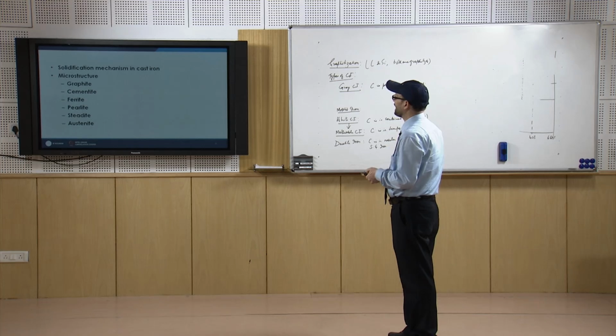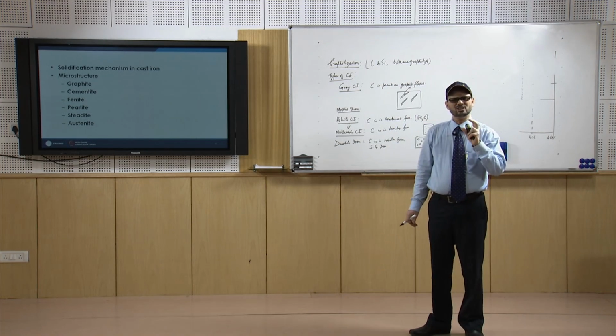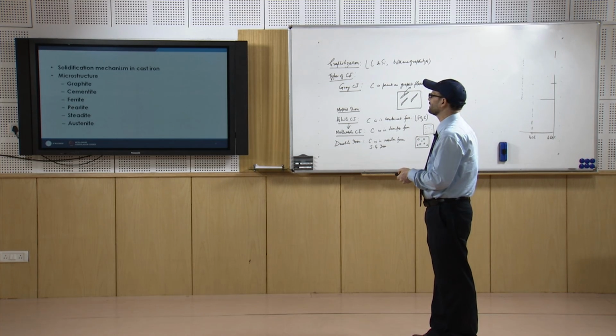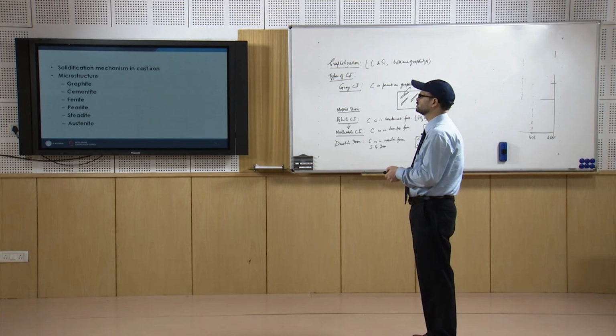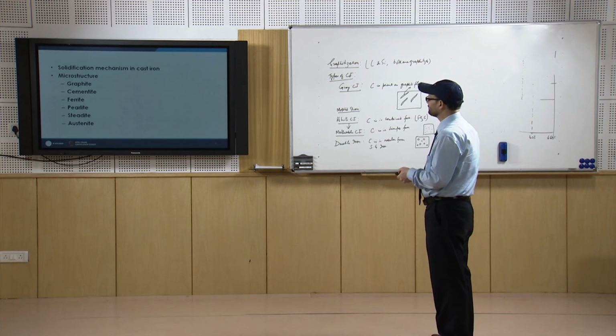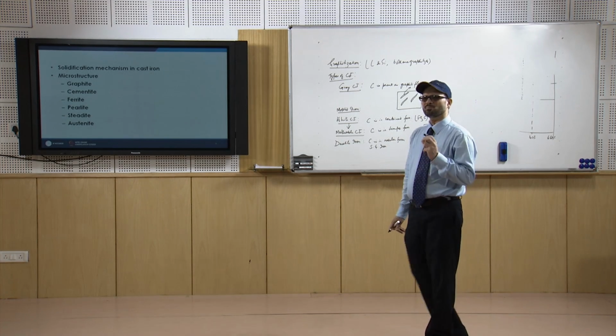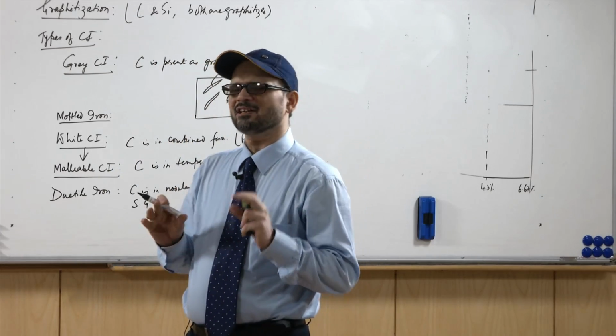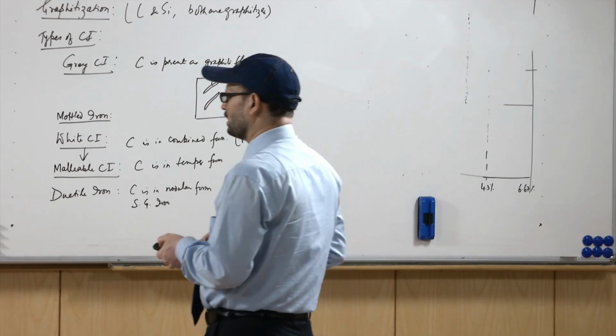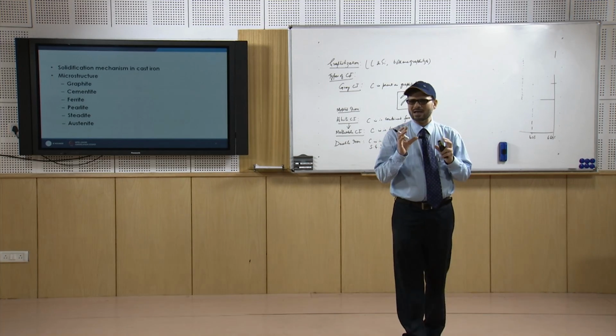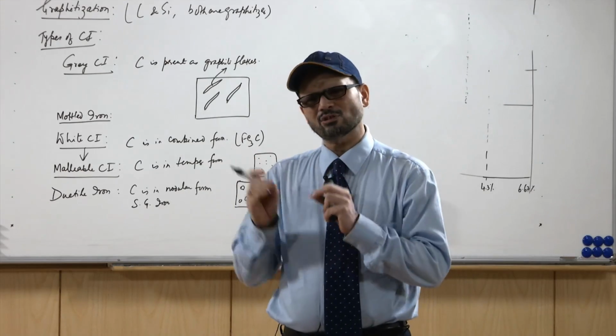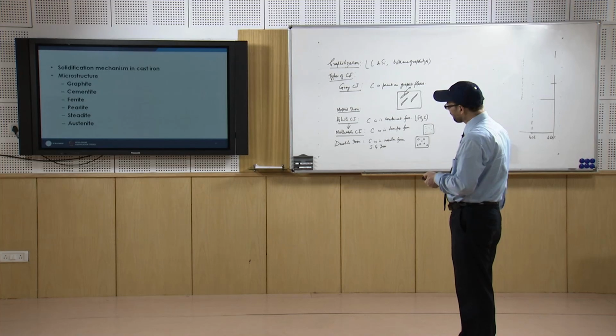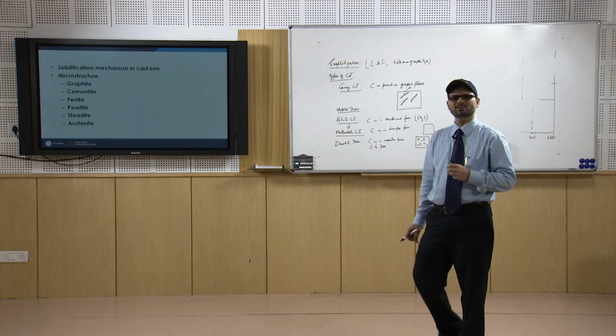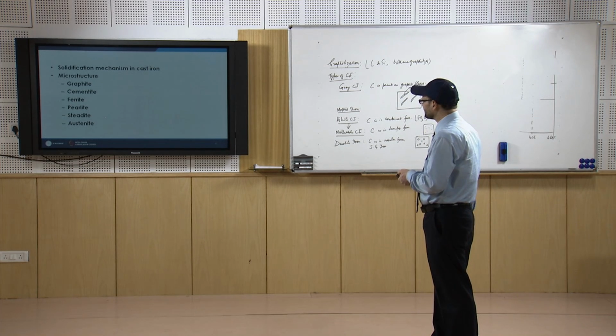Ferrite is a phase, as we have understood so far, that depending upon the extent of graphitization, you may have a ferritic matrix or a pearlitic matrix, or a combination of these two. Steadite is a phase which is nothing but a eutectic of iron and phosphorus, forming somewhere close to 1000 degrees or so. It has a very low melting point. Some of this is beneficial, and it imparts better fluidity to the cast iron. So, when the cast iron component is being cast in shallow or thin sections, some amount of phosphorus, because of this low melting point eutectic formation, may help give a large amount of fluidity.